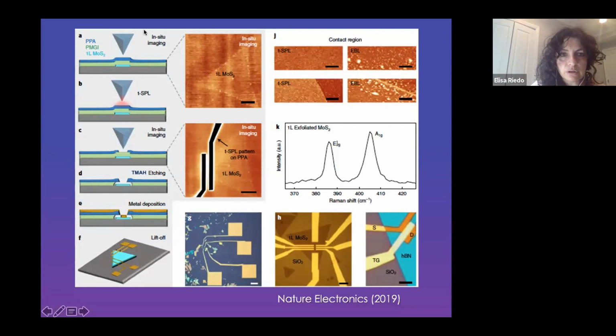Let me tell you, the idea is that you use a two polymer stack, PMGI and PPA, on top of a monolayer of molybdenum disulfide deposited on silicon oxide. You use t-SPL to evaporate locally the PPA, then you use some chemical etching for the undercut, and then metal deposition, and finally lift off. With that, you can pattern complex designs of electrodes on molybdenum disulfide.